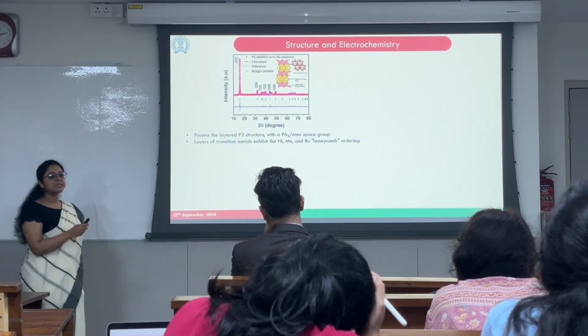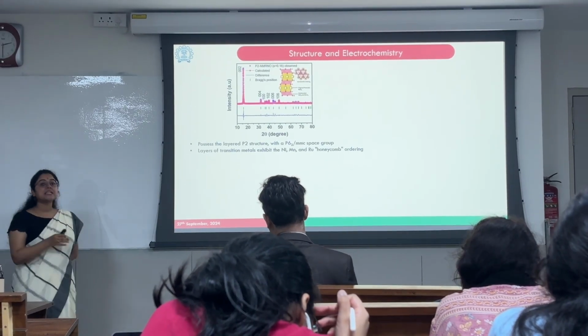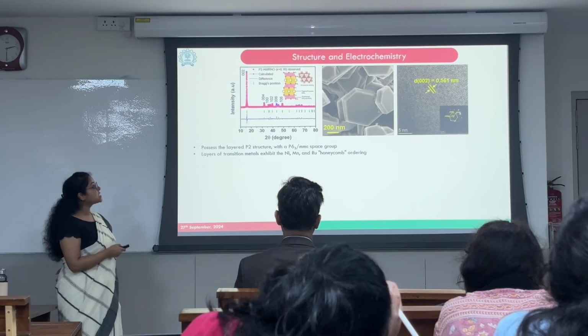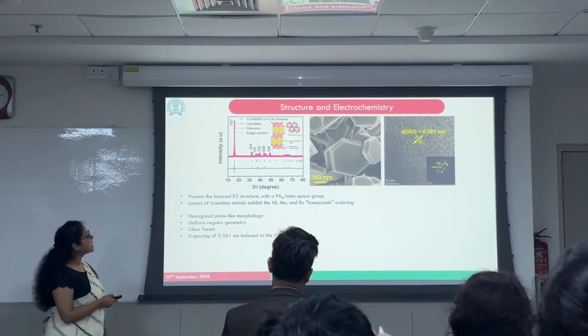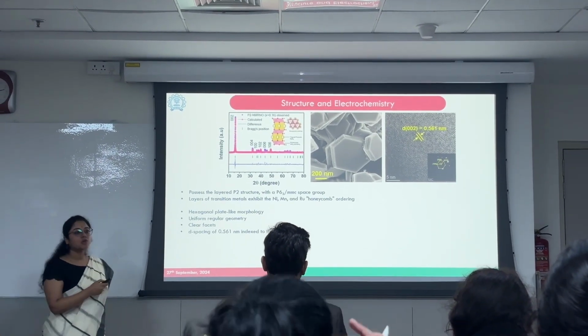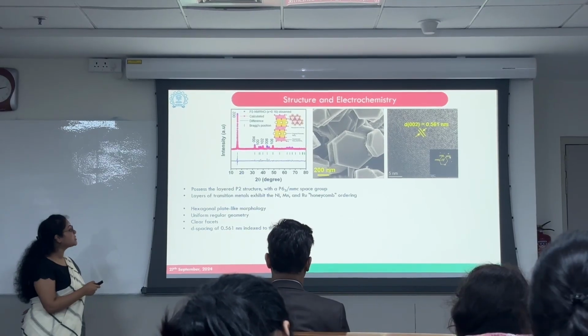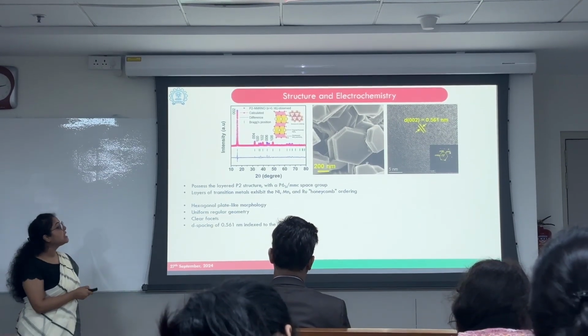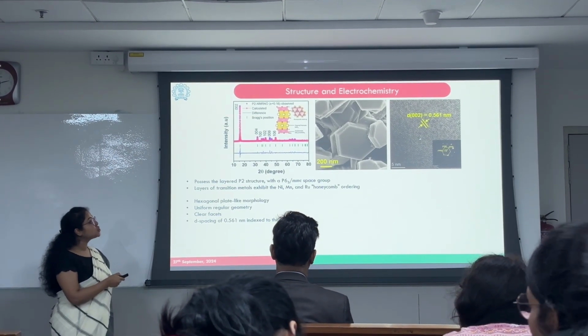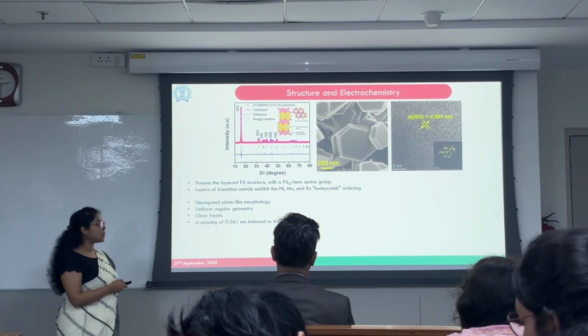And we could see through the XRD refinement that it belongs to the P63/mmc space group, and the nickel, manganese, and ruthenium have a honeycomb ordering structure. And through the SEM as well as the TEM analysis, we observed that a hexagonal plate-like morphology exists with very clear facets and uniform regular geometry, and the d-spacing for the 002 plane is 0.561.